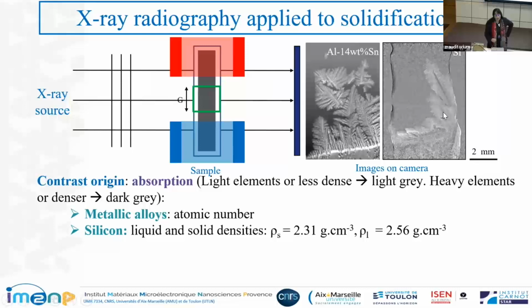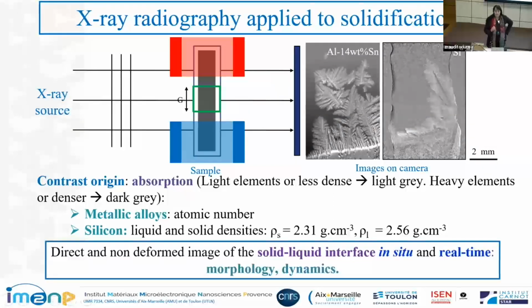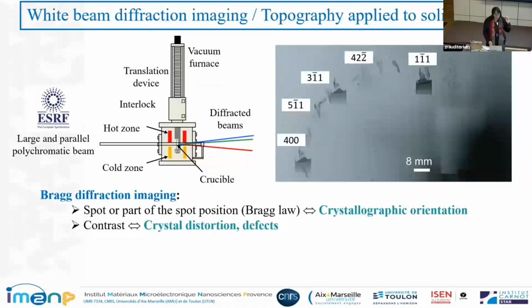In silicon, we have to rely only on the density differences between solid and liquid. And this is why we get this contrast between this solid region and this liquid region. With this, we have information about the solid-liquid interface in situ and real time, its morphology and its dynamics. This kind of experiments can in fact be done in laboratories if you restrict to lower temperatures, 600 degrees C. But if we want to go to higher temperatures, if we want to perform topography at the same time, we have to do this at ESRF, using synchrotron sources. And in fact, we do this at ESRF at the ID19 beamline.